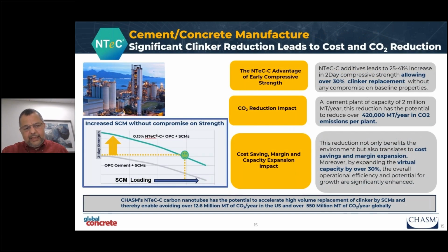And on the early strength, this is a graphic borrowed from one of our partners in the admixture area, where they commonly display a drop in early strength with, say, limestone addition, and what an admixture would do to compensate for it. And here I just brought in the perspective, my colleagues plotted this, of how it looks when you put the nanotube in, and how you can enhance SCM loading without the barrier of reduction of early strength. And hopefully this will increase the adoption.